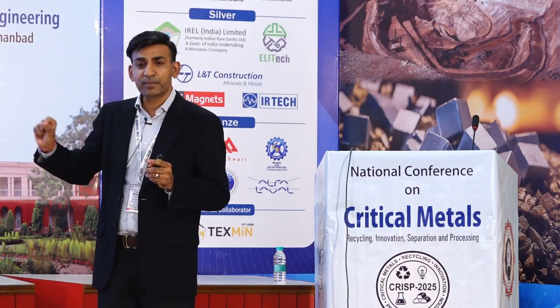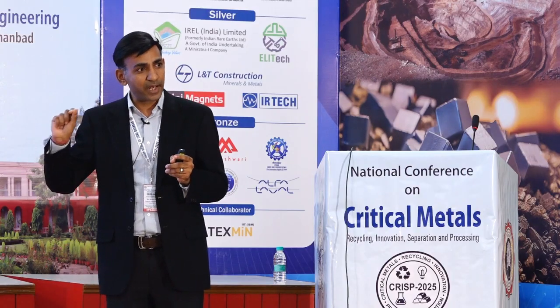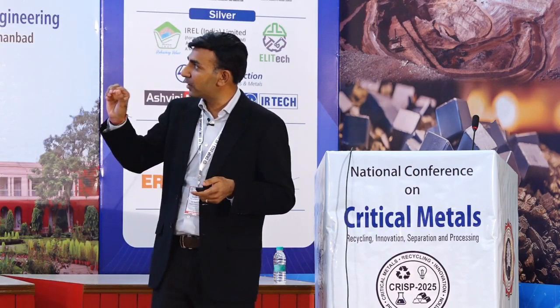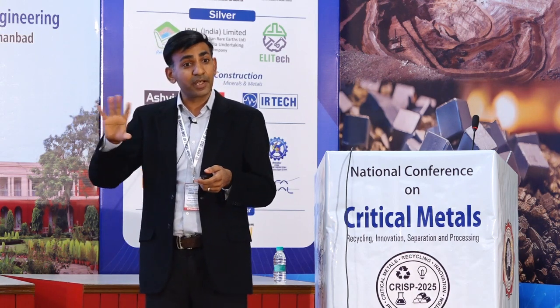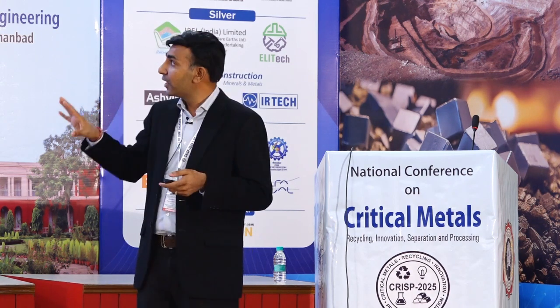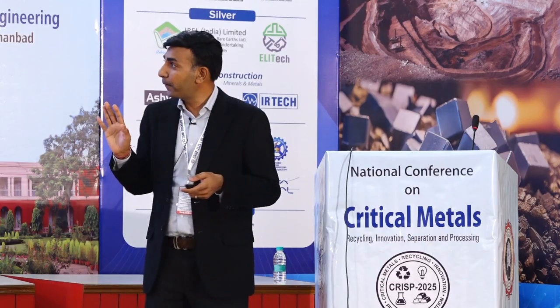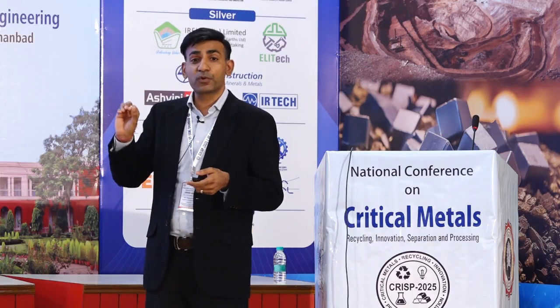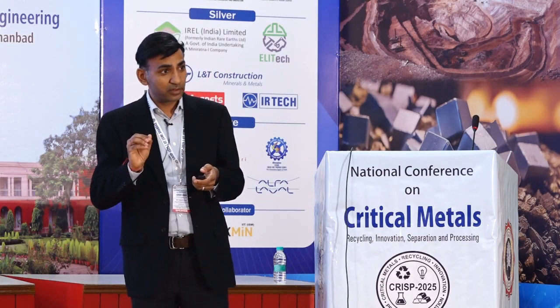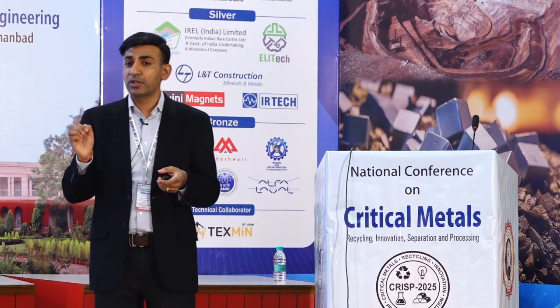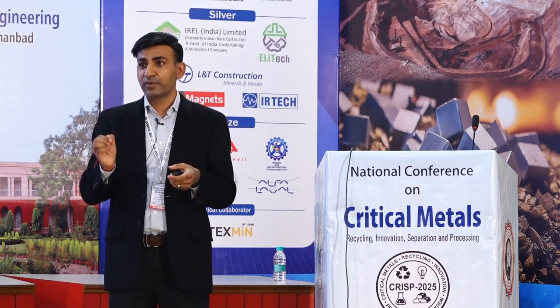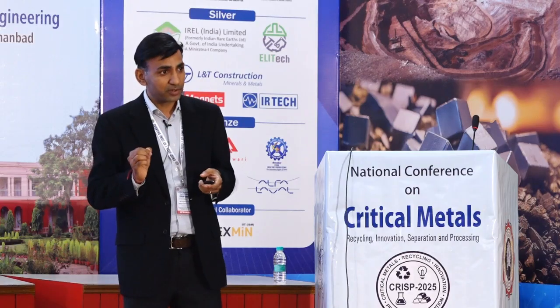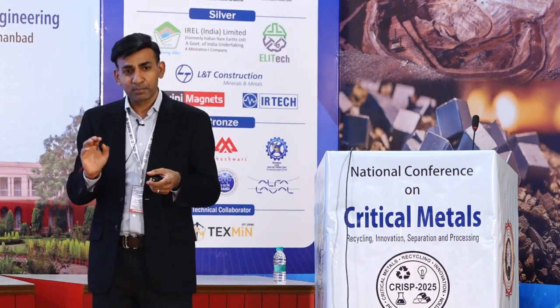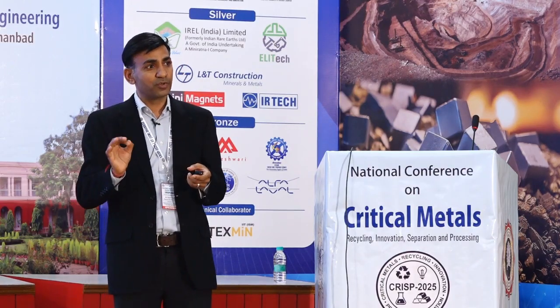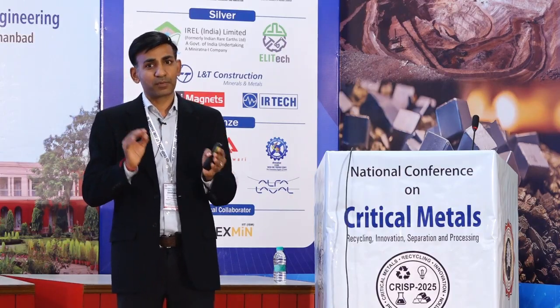We have developed an equivalent grade for Cyanex, with equivalent purity level, and it's already commercialized. It is a very good product for cobalt value. If you want a separation of cobalt and nickel with a high separation factor, it is a beautiful product. Cyanex, or our product, is a technology used for selective separation of cobalt from nickel.